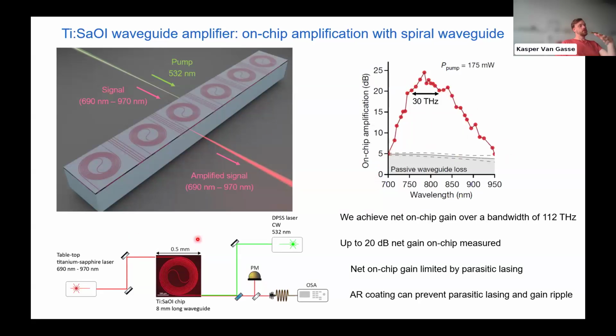So that makes this technology very interesting, that you can actually use this chip for almost any wavelength between 650 and 1100, all in this one technology. Moreover, the gain of titanium sapphire is extremely high. And for this 20 dB, we were actually mainly limited by the fact that the 7% reflection on the facets was already enough to make it lase if we increased the pump power. So that was one of the limits on the gain we could get, which could be improved by a lot just using a simple AR coating.